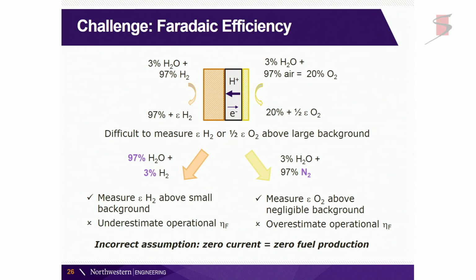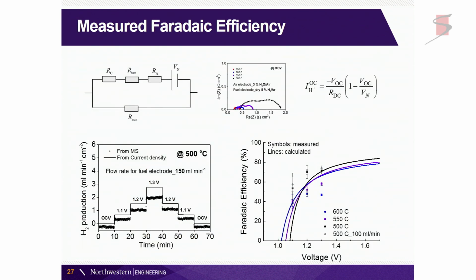And the incorrect assumption that happens is that at zero current, there's zero fuel production. So you might say, well, that makes sense. That's a very reasonable assumption. But in fact, at zero current, we have negative fuel production because we're just leaking a little bit of hydrogen across the membrane. Okay, so we do some electrochemical impedance spectroscopy to model our system, including a little bit of this electronic leakage and so on. We are now able to calibrate what we measure at our mass spec to be able to say how much the hydrogen production actually is.